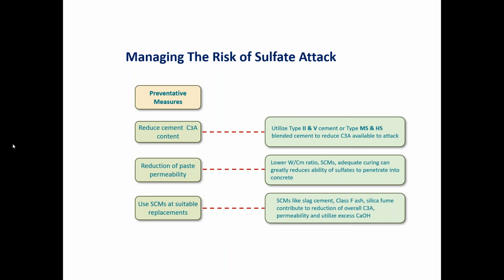The effect that they have really reaches both of those other two. One is that you get a dilution effect. If you take out a pound of cement and replace it with a pound of SCM, as long as that SCM doesn't contain C3A, then you're diluting or reducing the amount of C3A, which is very important for this whole process. You're also reducing paste permeability because these SCMs are later reacting components. They utilize free lime, which is another component we said is used by sulfates to attack concrete. They utilize the free lime, then have a delayed hydration reaction, and then further densify the paste, so they reduce the permeability. So SCMs are a very good thing when they're available and when they are of proper quality. So next slide.